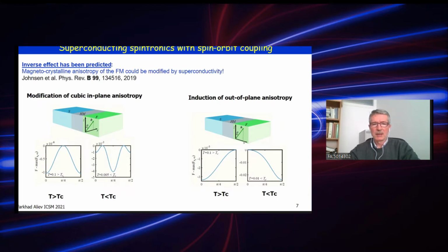For example, for in-plane anisotropy, below TC the hard axis 110 can become dominant, and out-of-plane anisotropy will also be stimulated, depending on the conditions of competition between in-plane and out-of-plane anisotropy, which we consider in our experimental case.